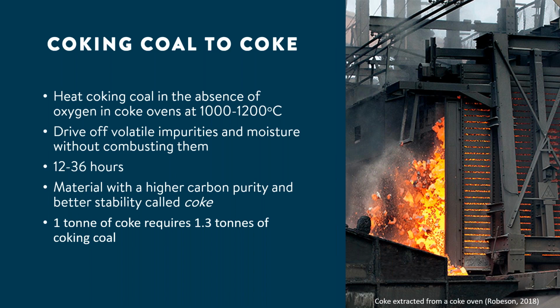Low rank steam coals can be used, but generally lead to poorer quality cokes, albeit cheaper to buy, but smaller amounts can be used without doing too much harm. Now, the coke is then extracted and quenched before it goes to the blast furnace, and it's important for the coke to be a stable mass rather than a friable mass. It needs to form a structure in the blast furnace that permits gases to pass through the bed of coke and ore, a bed of hot solid material, for reduction of the ore to take place.